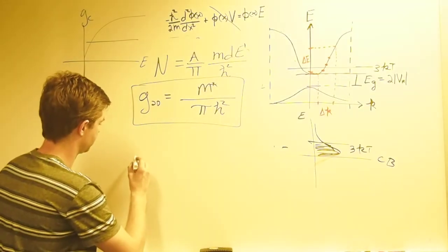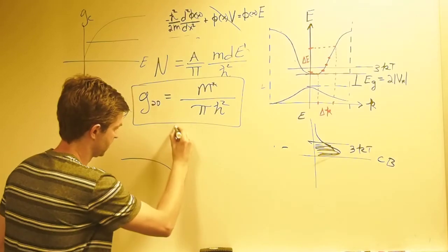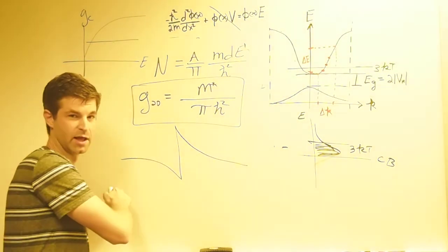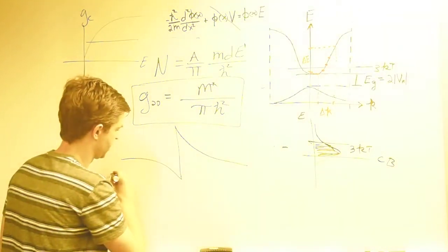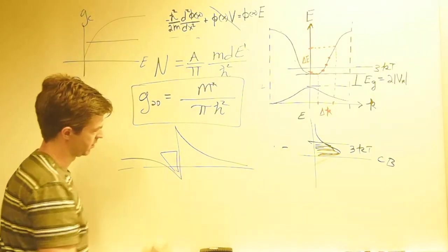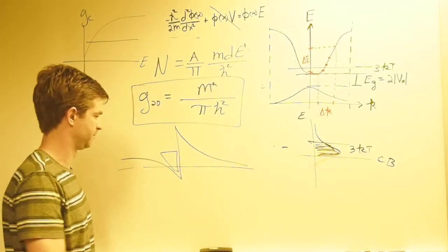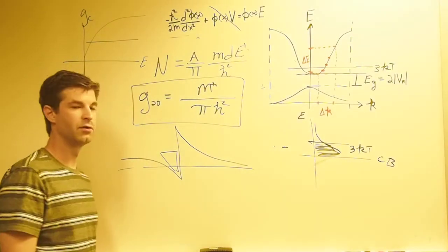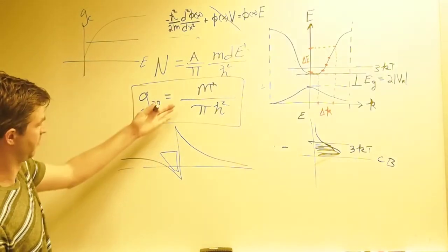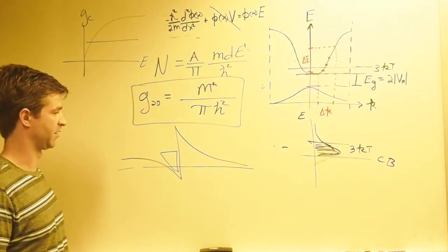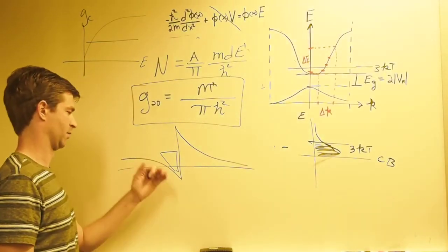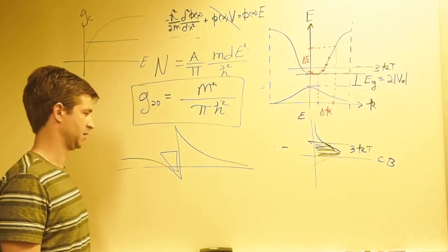If this is GaAs and AlGaAs, gallium arsenide and aluminum gallium arsenide, doped to Fermi levels here, well, in this region right here your electrons act as a 2D electron gas, and so in this space you have a two-dimensional density of states. So here you have very high mobility and a lot of other really cool characteristics, in EC.